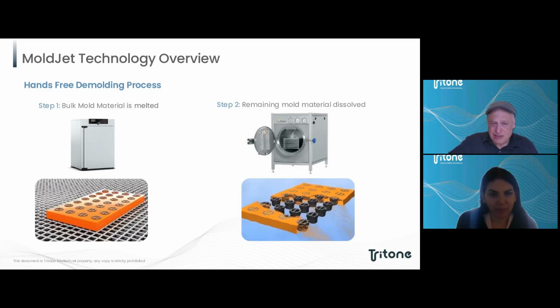The downstream process, demolding. There is no depowdering operation because there is no loose powder. There's nothing to depowder. The parts, simply the mold block, if you will, is taken to a 2-step demolding process. We melt the bulk of the wax and dissolve whatever is left over from the material. That leaves us with those tough green parts we spoke about earlier.